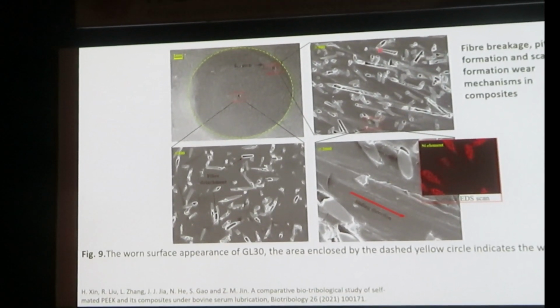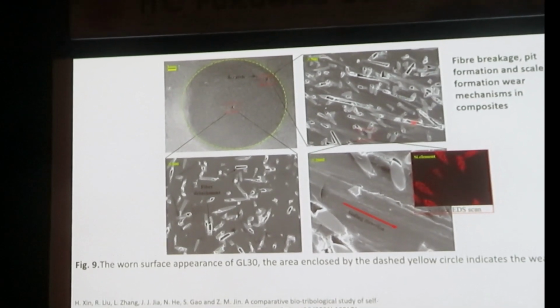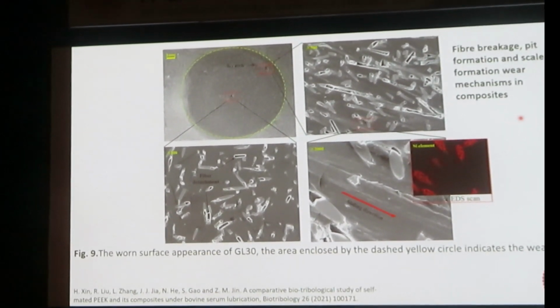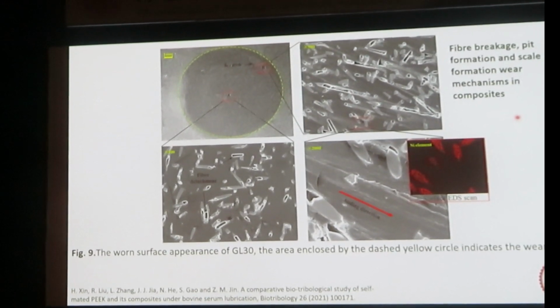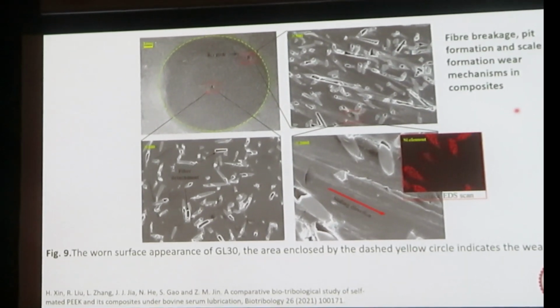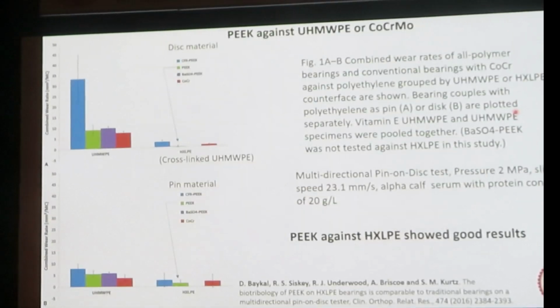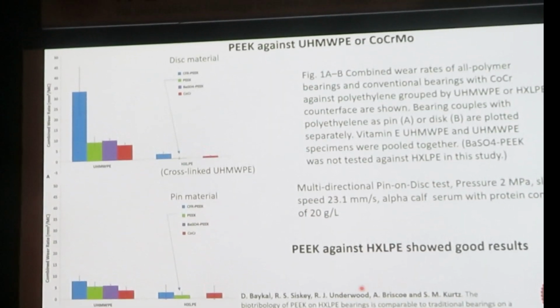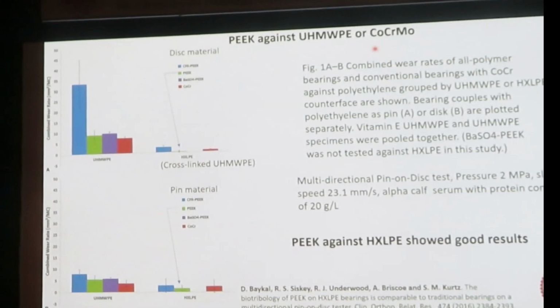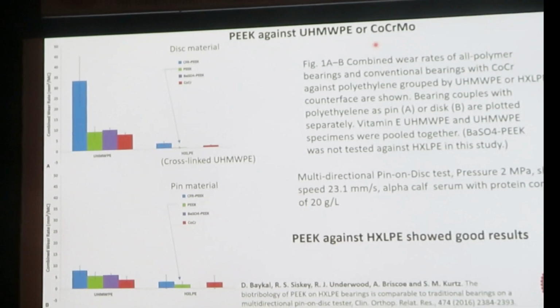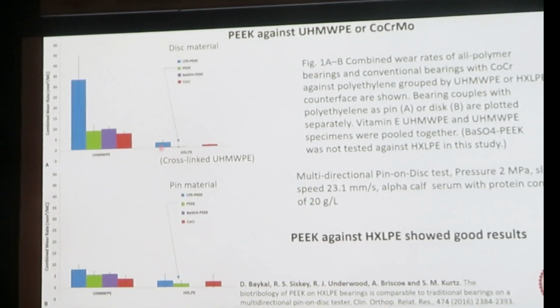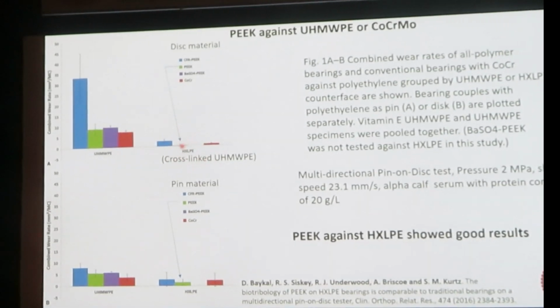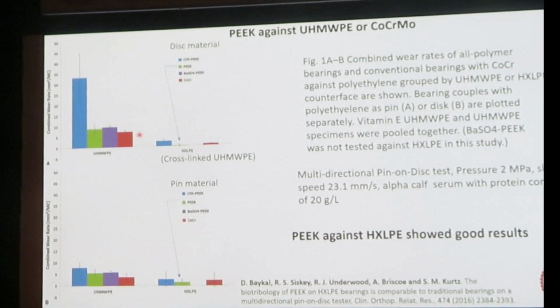They just show the surfaces, but the failure is still the same type, as you can see. The fiber pull out from the surface is again quite worrying for biomedical applications like joints. Another thing they found is that PEEK has better performance when polymer is sliding against polymer, against itself or against UHMWPE. In another research, people again tried PEEK against UHMWPE and against cobalt chrome molybdenum. In that case, people found that PEEK against UHMWPE or cross-linked UHMWPE has extremely low wear compared to all other conditions.